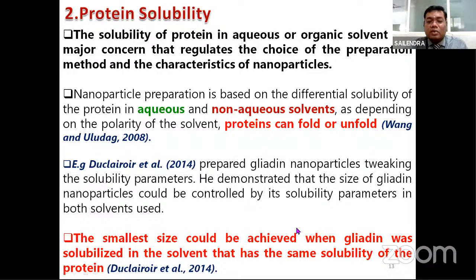Duclairoir et al., in the year 2014, prepared gliadin nanoparticles coming from a plant source, and tweaked the solubility parameters of the protein, modified it slightly, and demonstrated that the size of gliadin nanoparticles could be controlled by its solubility parameters in both solvents used. So you're using water as one of the solvents, and one organic solvent. If you control the solubility parameters in such a way, how it is precipitating in one solution, how it is precipitating in another solution, definitely you will have control on the nanoparticle size.